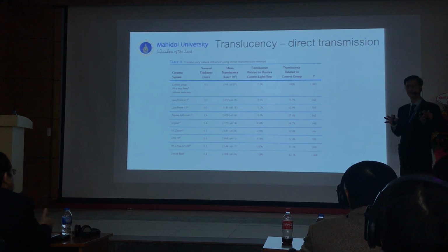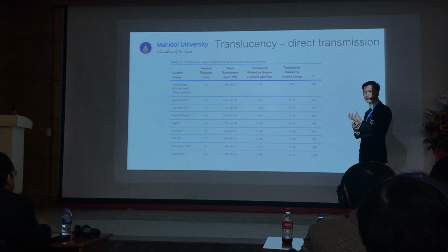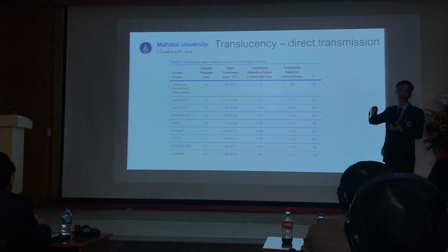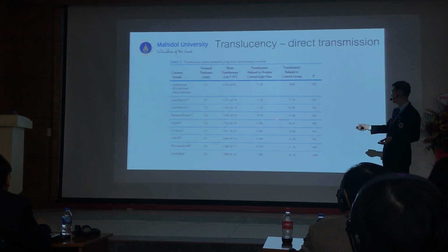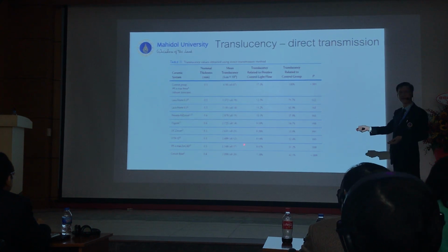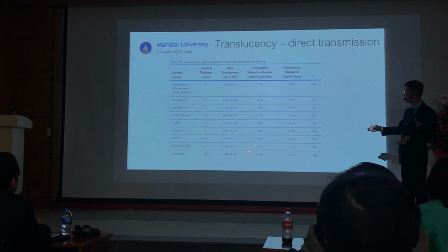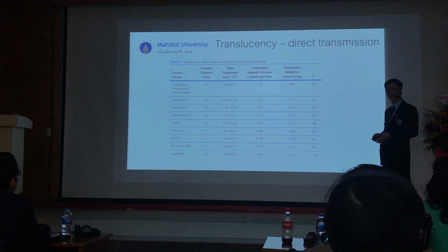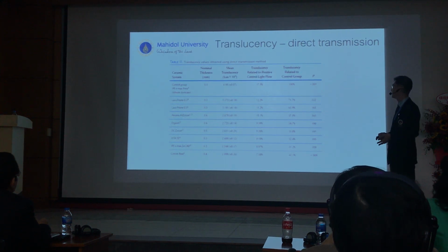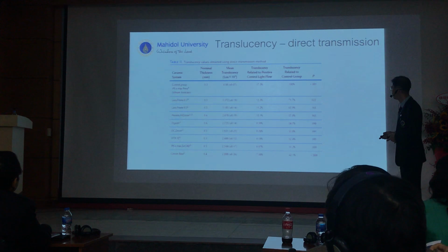But because of the crystal structure, one crystal is going to be very clear, but zirconia has a lot of crystals. The light cannot pass through a lot of crystals, because when it meets the grain boundary, the light sometimes reflects back and sometimes is absorbed at the grain boundary. So the light can pass through zirconia around 10%, compared to e.max around 20%. So e.max is like a standard for the translucency property of the material.